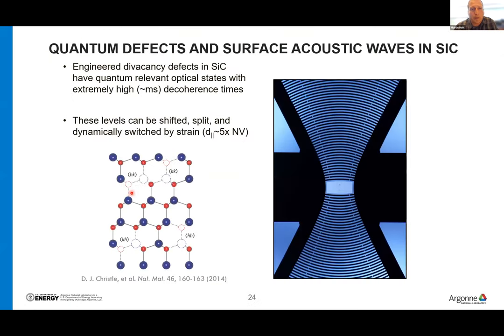Okay, acoustic dynamics. So this is looking at silicon carbide divacancy clusters, which are optically active defects that have good quantum behavior up until room temperature and relatively high coherence. They interact with the strain quite strongly and the speed of sound is isotropic. So the University of Chicago folks and David Awschalom's group were able to create these cool Gaussian focusing resonator structures that drive acoustic waves through these materials. And then mechanically you can dress the spin states and use them to flip spins.